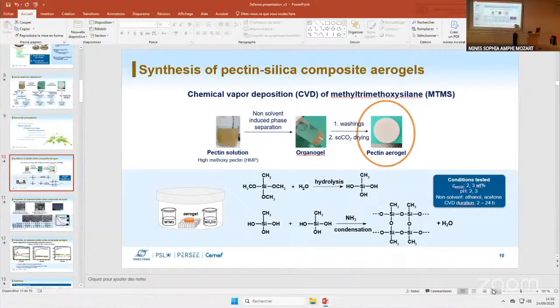When we tried to modify with HMDS, we did not do supercritical drying in some cases, and we did not see any structural changes chemically from FTIR. Okay, so that answers that concern. So basically, we believe that it does not occur for pectin at least, or maybe we did not find good conditions. But then what he also saw, and that's also why MTMS is probably the right strategy, is that this bond is then weak. You depend on one single silicon oxygen carbon bond, which hydrolyzes relatively easily. So long-term hydrophobization might not be that good.